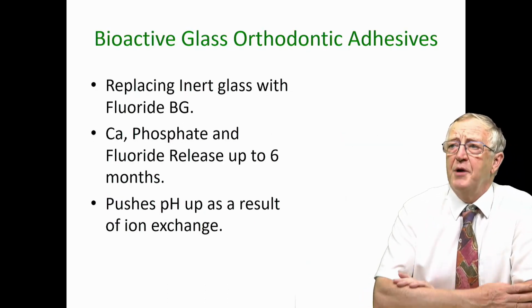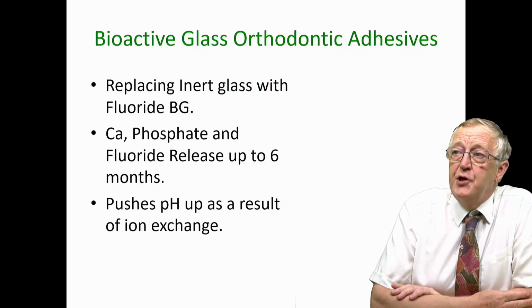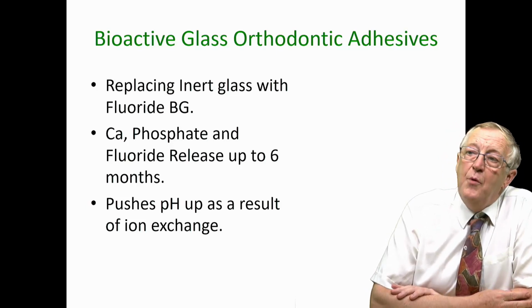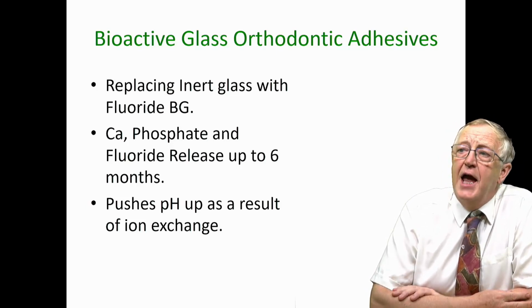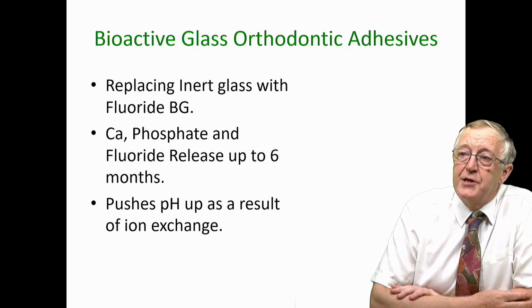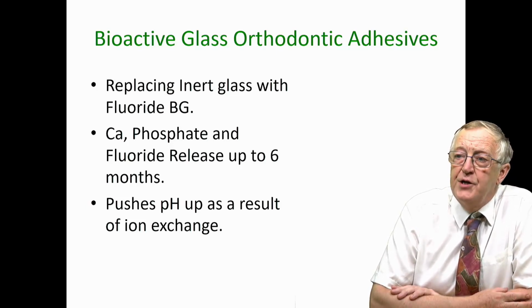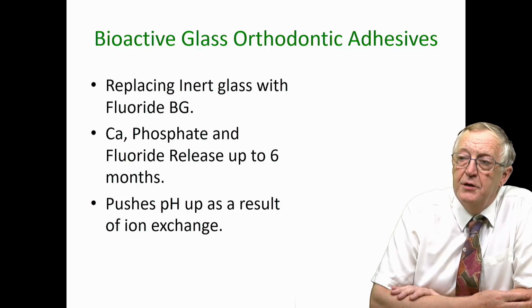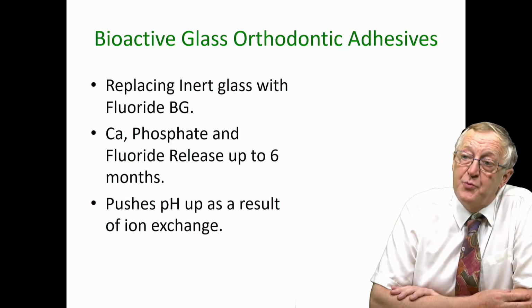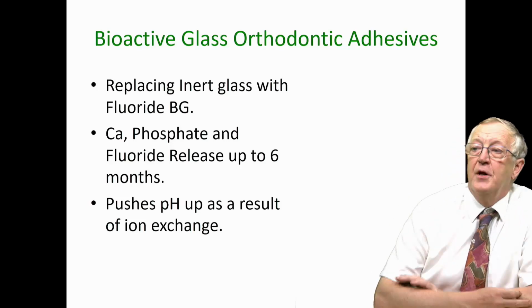We're going to look now briefly at the use of bioactive glass in an orthodontic adhesive, and we're replacing the inert glass again with a fluoride bioglass. And we have calcium and phosphate and fluoride release out to 6 months. We haven't measured it any longer than that. And we also have a pH rise.